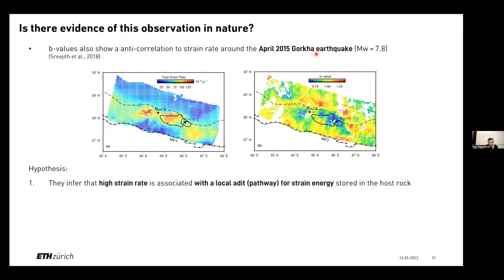This paper in 2018 on the Gorkha earthquake shows the strain rate in regions local to the M7.8 hypocenter was increasing and the B value was decreasing. So this is preliminary, but their hypothesis is that high strain rate is associated with a local conduit or a pathway for the strain energy stored in the rock mass. And this is a nice result.